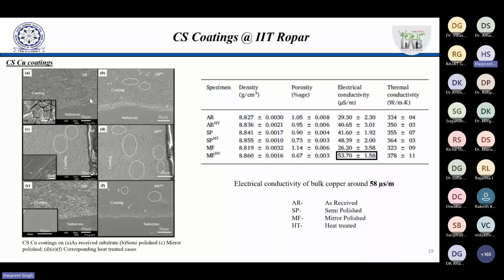When I say thick, they want 3 mm thick coatings of copper, right? And that has to be pure, because their purpose is not for corrosion or any other thing, but they are using these coatings for passivation of plasma currents, for which they want very good thermal and electrical conductivity in the copper coatings. Now, this was a magnanimous task, that 3 mm thick deposit of pure copper has to be developed, right?